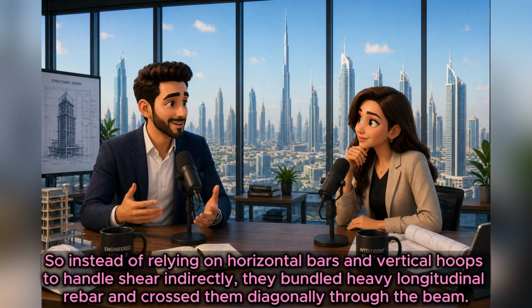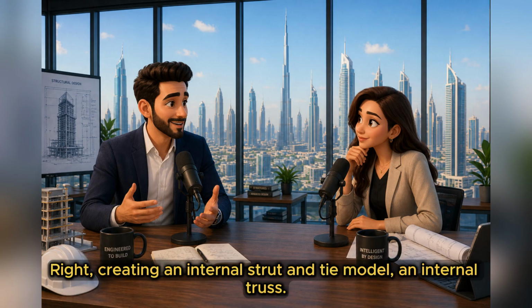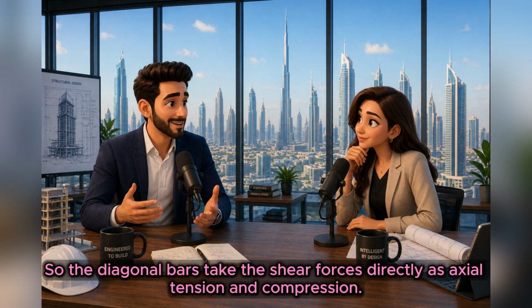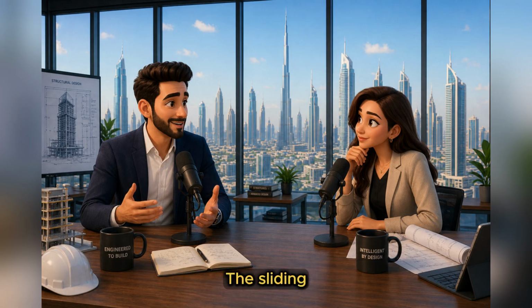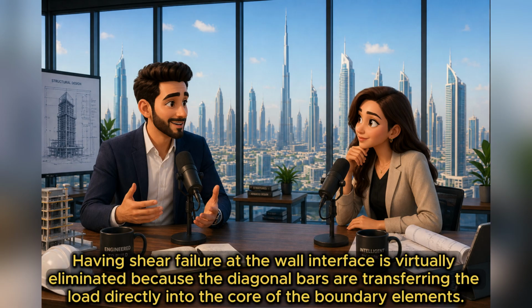So instead of relying on horizontal bars and vertical hoops to handle shear indirectly, they bundled heavy longitudinal rebar and crossed them diagonally through the beam. Right, creating an internal strut and tie model, an internal truss. So the diagonal bars take the shear forces directly as axial tension and compression. Exactly. The sliding shear failure at the wall interface is virtually eliminated because the diagonal bars are transferring the load directly into the core of the boundary elements.